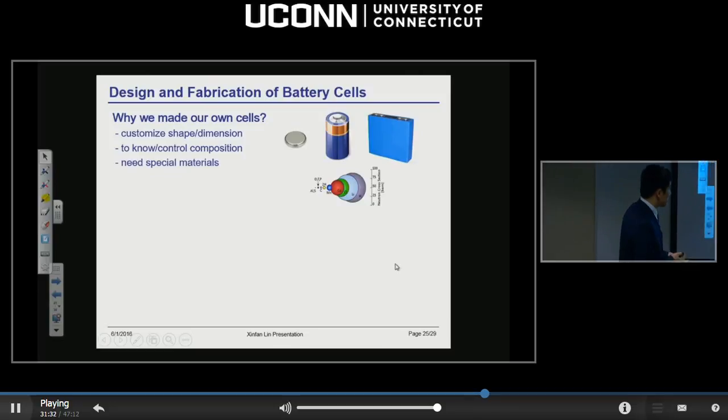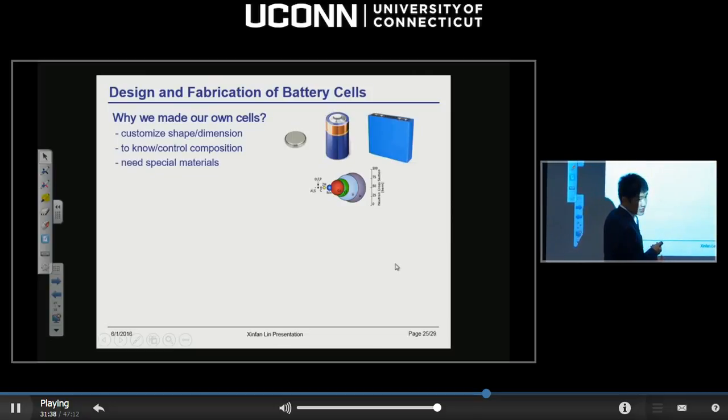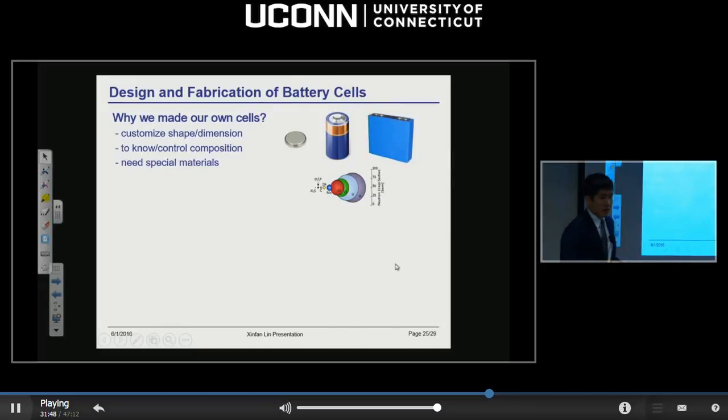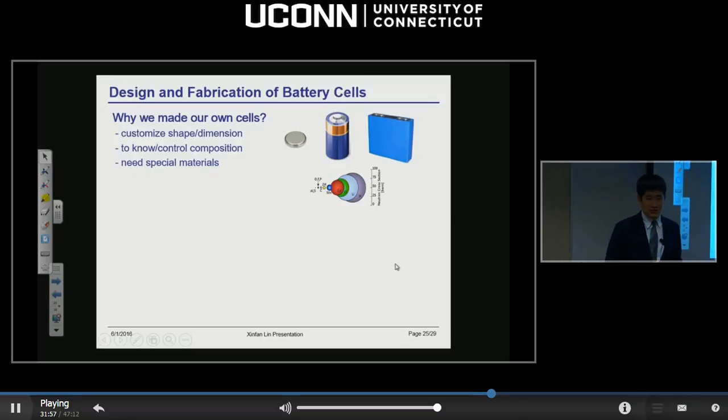This is because, let's go back to the schematic here. I didn't mention previously that hydrogen actually has the largest cross-section, and hence the strongest ability of blocking the neutrons. This is why it is used so much for neutron imaging of fuel cells. Therefore, if we have too much hydrogen in the lithium batteries, it may basically block out everything, so we probably would not see anything on the detector.